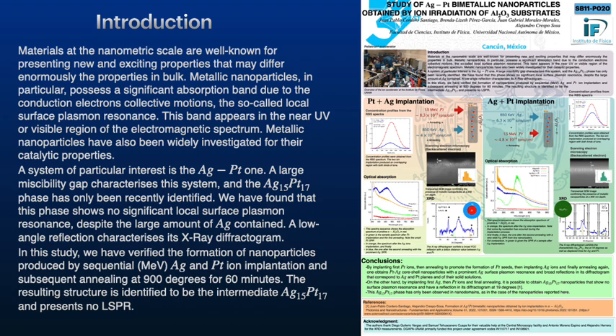A system of particular interest is the silver-platinum system. A large miscibility gap characterizes this system, and the Ag15Pt17 phase has only been recently identified. We have found that this phase shows no significant local surface plasmon resonance, despite the large amount of silver contained. A low-angle reflection characterizes its X-ray diffractogram.